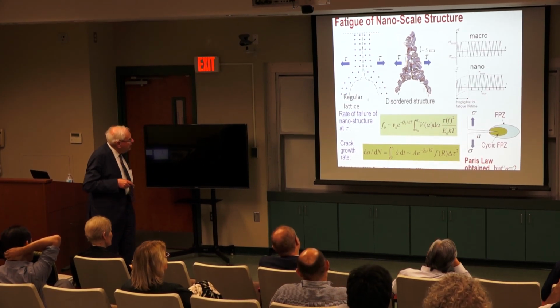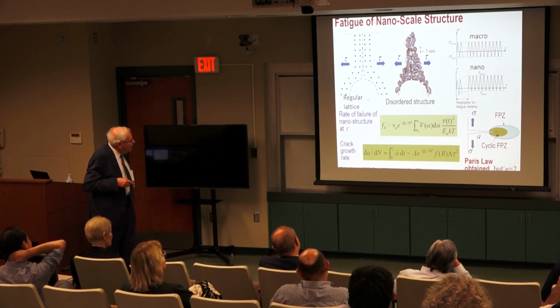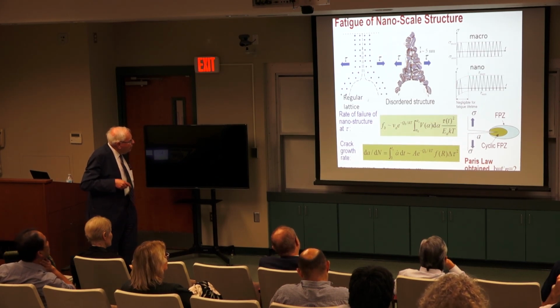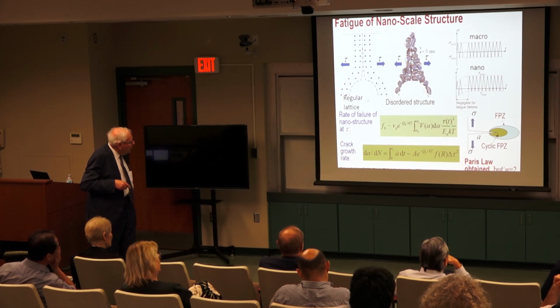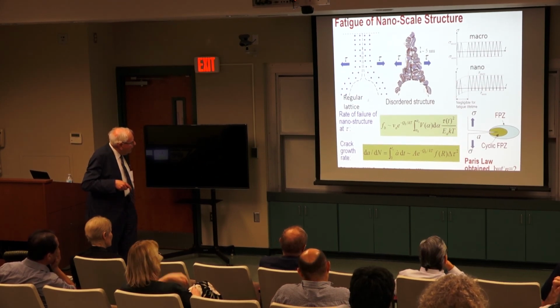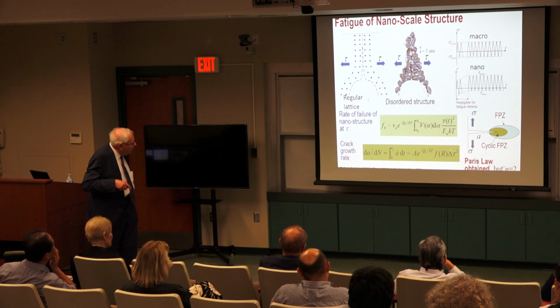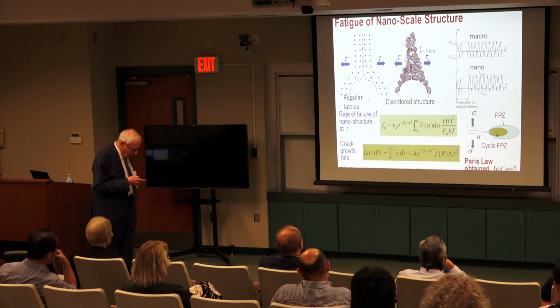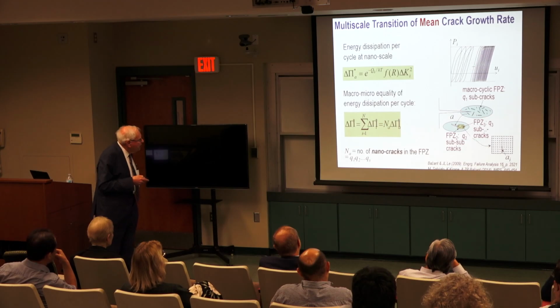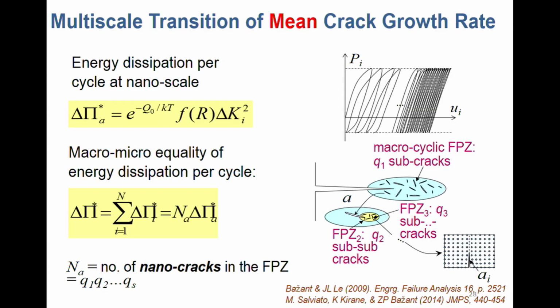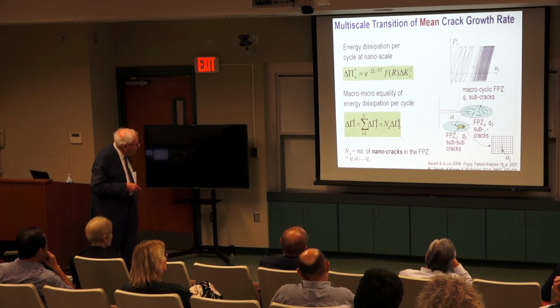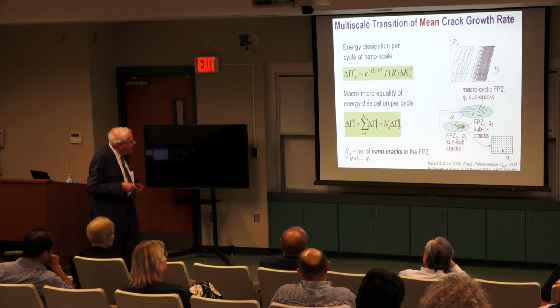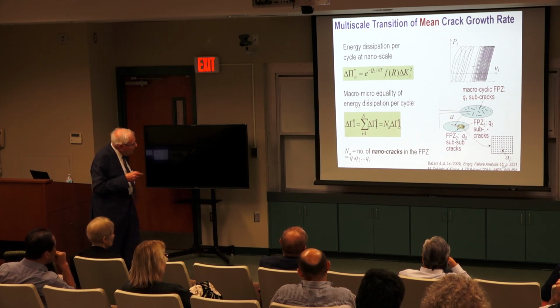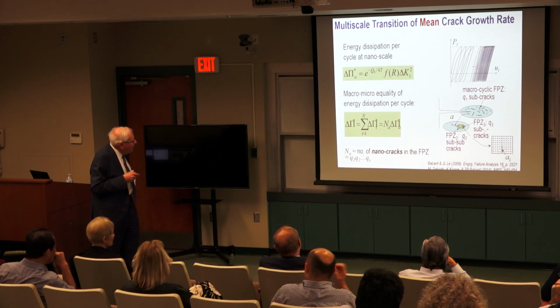You need to integrate it over a cycle, and you obtain a law by the integration that the advance of the crack is again proportional to the square of the imposed stress. Now what has to be noted here is that all these cracks at one scale have subcracks at a smaller scale, which have subcracks, until you go to the nanoscale. It's impossible to calculate exactly, but we can argue about the tails again simply. But here we must argue a different way.